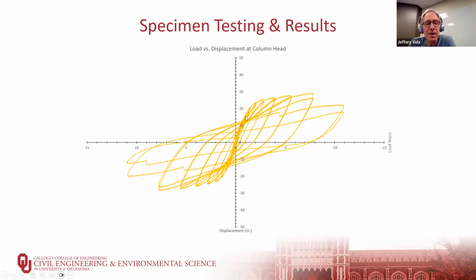You have initial linear elastic response when the deflections are low. All the materials, the steel and the concrete, are behaving linearly elastically, which is great, which is exactly what it should do. At some point, you begin to crack the concrete in tension. And because it's a cyclic loading where you go in both directions, you're going to crack it on one side that's in tension, and you're going to crack it on the other side when you reverse the load. So eventually you start to become nonlinear once you crack the concrete.